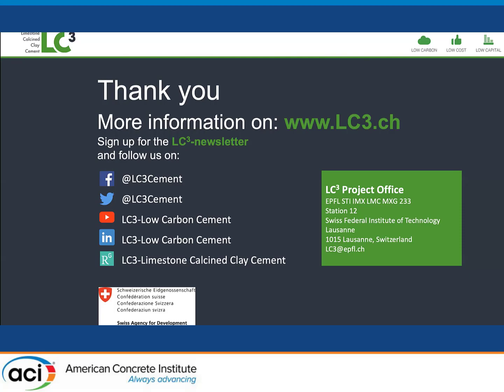Kashir Jafari says, great talk. What is the reason or mechanism that calcined clay mixtures show higher strength at early ages compared to other mixtures? Well, it's just very simple. It's just because the calcined clay is way more reactive than things like fly ash and slag. And the answer for that is that fly ash and slag are kind of glassy materials, so they only can react on the surface. Whereas a clay, it's a layer structure, so you've got a way higher surface area that can react. And because it's not a glass, it doesn't have to kind of dissolve in the same way. It's really more a disruptive structure, and all of these contribute to a much higher reactivity.